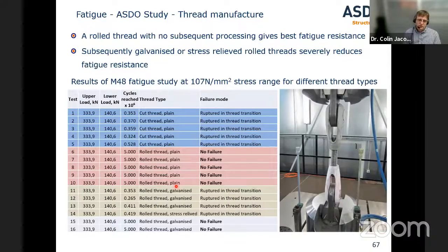And we also conducted a number of tests where we took cut threads and rolled threads, and we just cycled them up to 5 million cycles. What we found, as we expected, was that a cut thread really only got up to about maybe 300,000 to 500,000 cycles before it failed. With a rolled thread, we couldn't make the bar fail after 5 million cycles. But if we galvanize that rolled thread, then again, we get similar fatigue resistance to a cut thread.